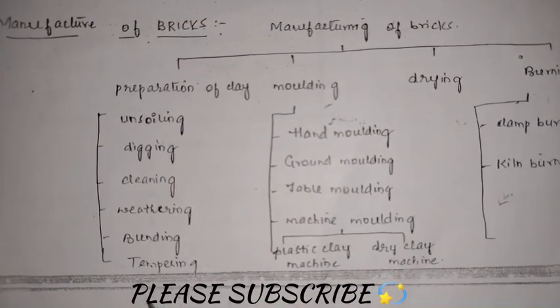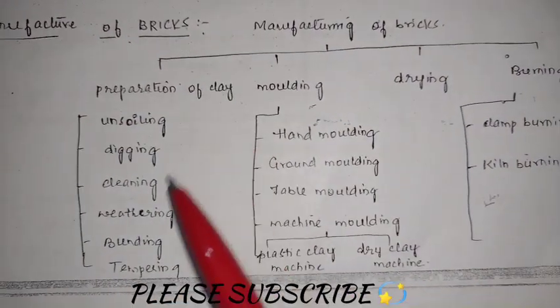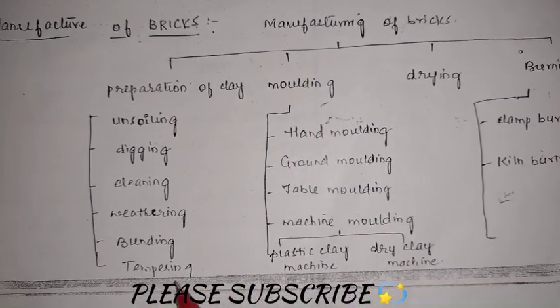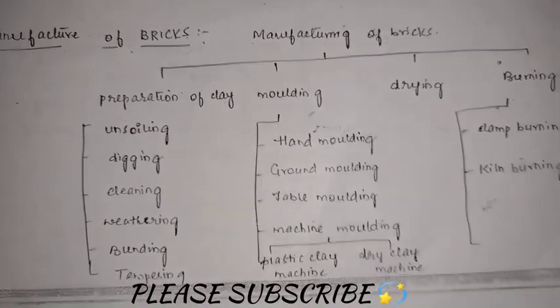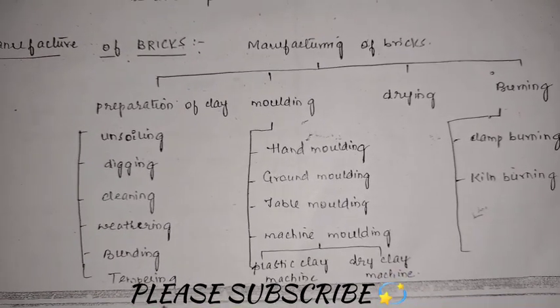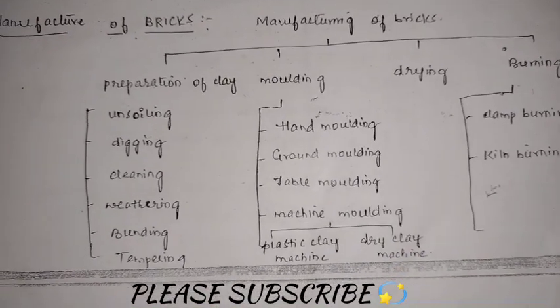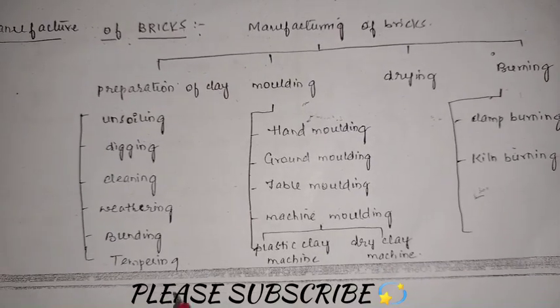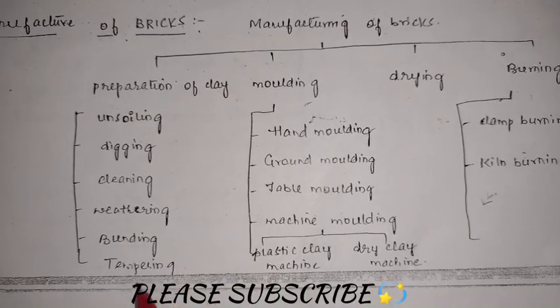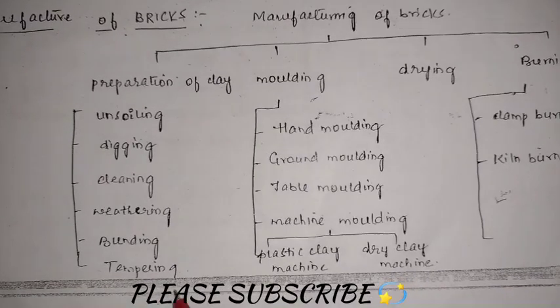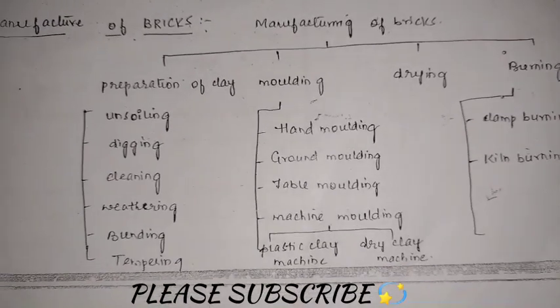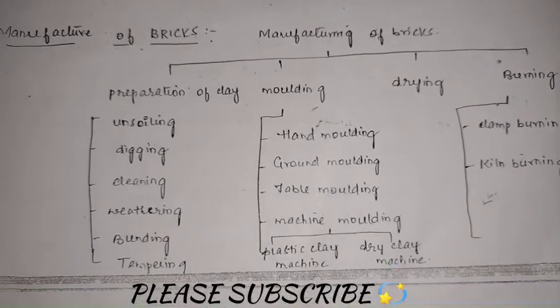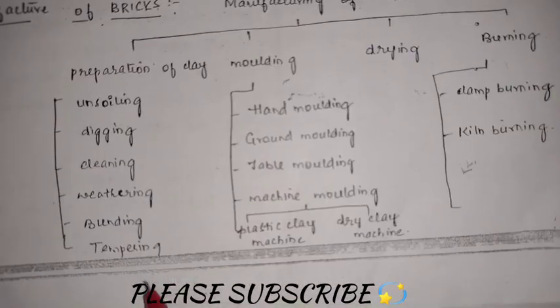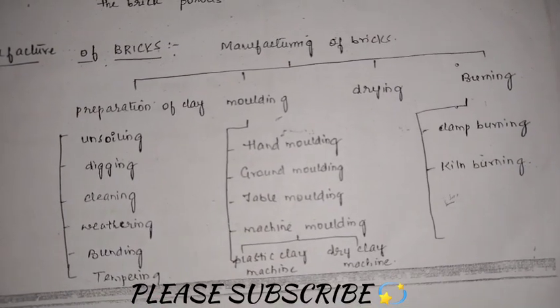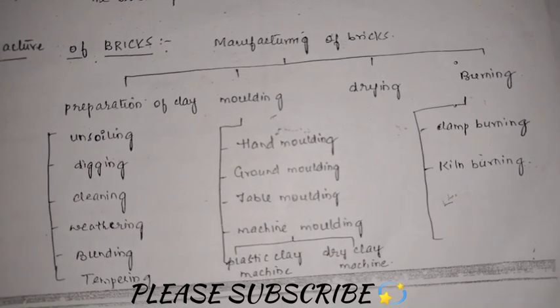Coming to the last subtopic in this preparation of clay, that is tempering. After blending, a required quantity of water, that is about 1/4 to 1/3 by weight of soil, is added to the soil and the entire mass is kneaded thoroughly to obtain homogeneous mass of brick earth. So here we are ensuring the uniform character of the brick earth by adding 1/4 to 1/3 by weight of soil water and mixing it thoroughly. This mass of earth is allowed to dry gradually till it becomes stiff and plastic enough for proper molding.